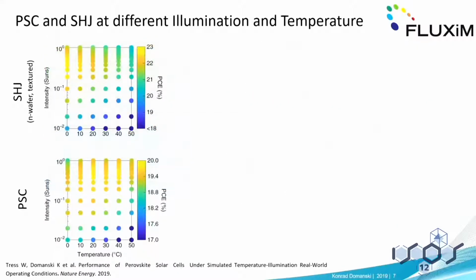So what we did at the beginning is we explored the parameter space of temperature and illumination. And we looked at how perovskite compared to a silicon heterojunction cell, which was fabricated on an N-type wafer, fully textured, and how they behave across this parameter space. So we see for the silicon, as we go to lower temperatures and higher illumination, at least to some extent, we increase our efficiency. For perovskite, we could only find the trend with illumination, and we didn't find one for temperature.